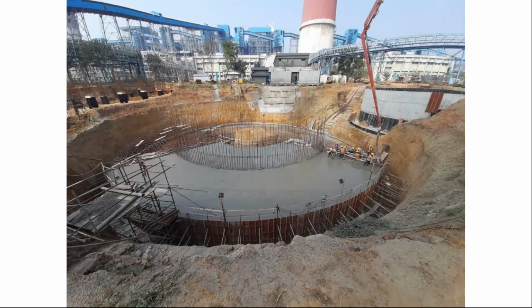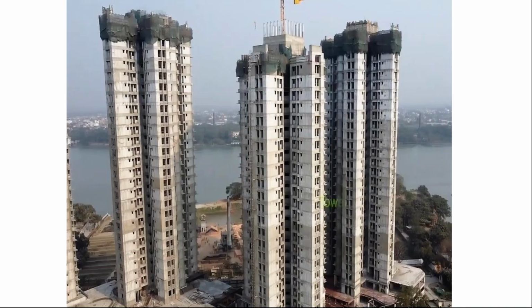Now, this is a kind of mass concreting happening within a thermal power station, where you will find that when there is mass concreting, the heat of hydration is very critical. So the heat of hydration has to be defined. Many critical projects of this kind would demand it. Either the heat of hydration would be measured, or the concrete temperature would be measured, maybe at the time of pouring, maybe after some time. So these kinds of parameters are being monitored.